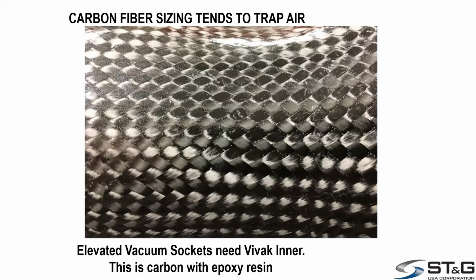So if we look at this picture of carbon fiber braid, we can see that there are some air bubbles in it. Sometimes air bubbles are generated because of an incompatibility with the resin. Also, sometimes you have so many threads, like a 12K carbon, and yet it's all coated, and sometimes that in itself will trap air. Also, it could be if you're using acrylic, if you mix it incorrectly or try to make it cure too fast, it can also outgas.